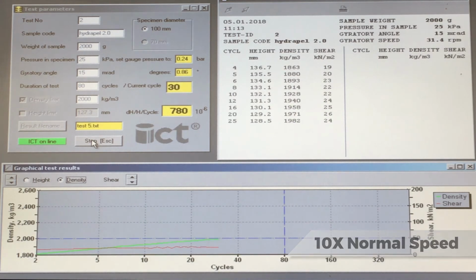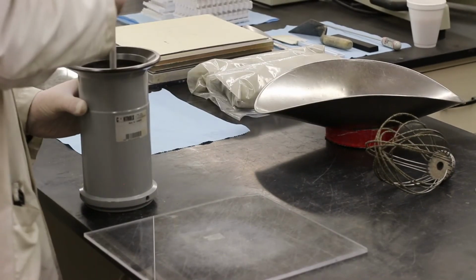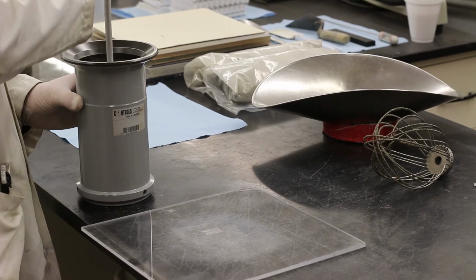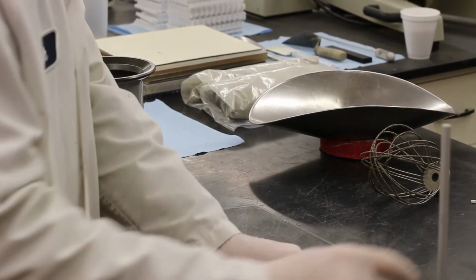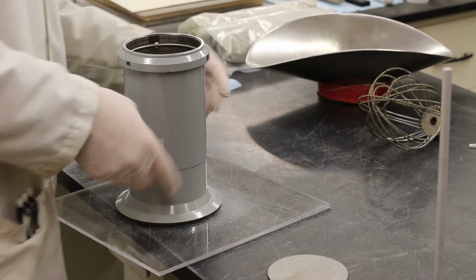In this demonstration, 50% fewer compaction cycles were needed to achieve the same target density. Reduced friction during strip out is also dramatic. This translates to mold life extension and further cost savings.